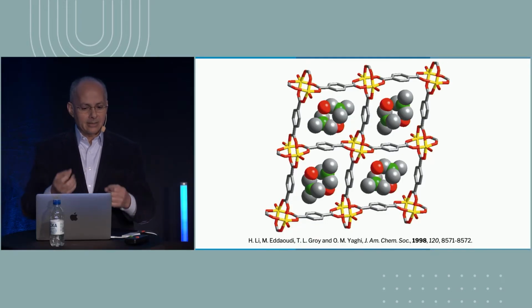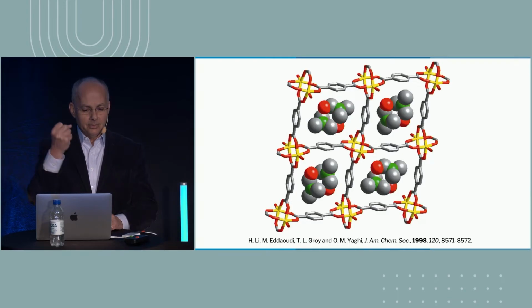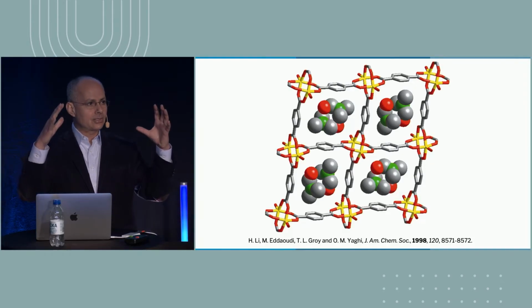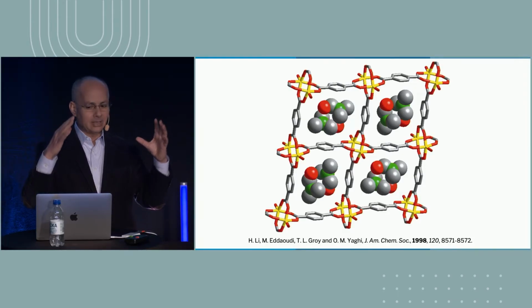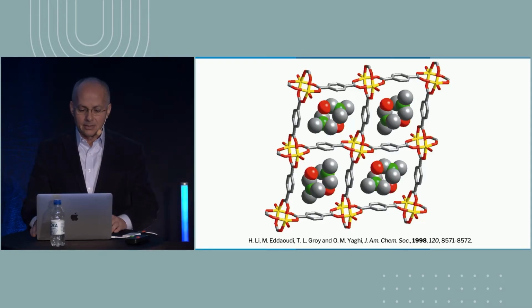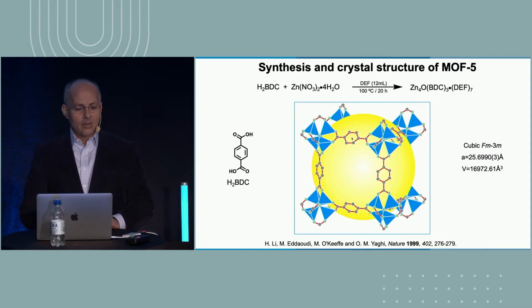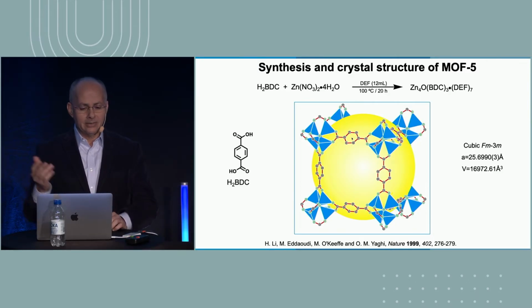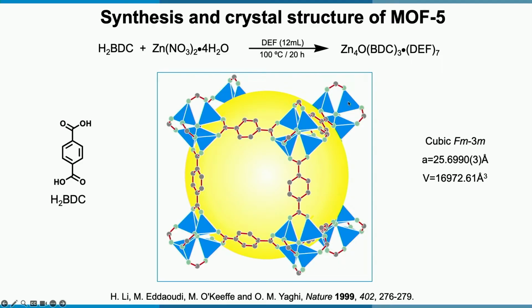Okay, and so then later we showed that in fact you could remove these DMF molecules and the structure still stands. Okay, and I'll show that shortly. Well, all right, if you can do one reaction, you can do the other. Turns out that DEF, diethylformamide, when you heat it, it produces very small amounts of triethylamine. That triethylamine can deprotonate the acid slowly, and you can make this kind of cluster or a crystal.